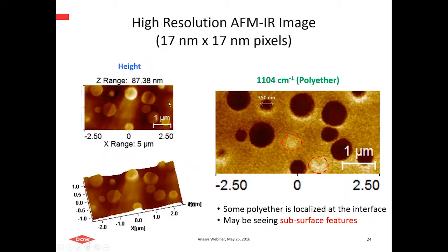We can take higher resolution maps, and when we do that, we find some interesting things. We start to see potentially enrichment of some of the polyether functionality at the circumference of these rigid domains, as well as what we think might be subsurface features that are not shown. For instance, these 2 locations, if you look in the height image, we don't really see any perturbation topographically at those locations, but spectroscopically we're picking something up. These might be buried domains below or something like that, but that's intriguing to us as we think about how deep we might be able to see with the technique.